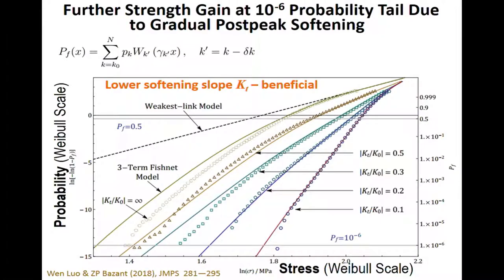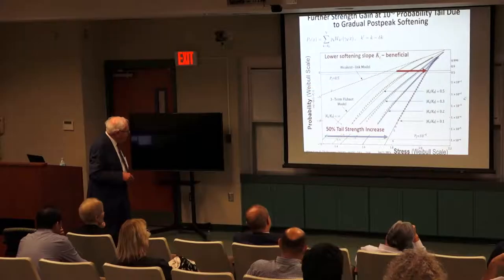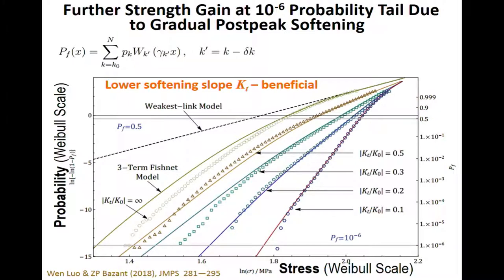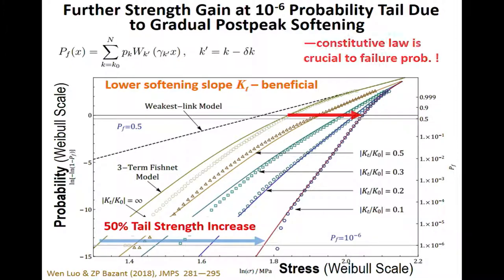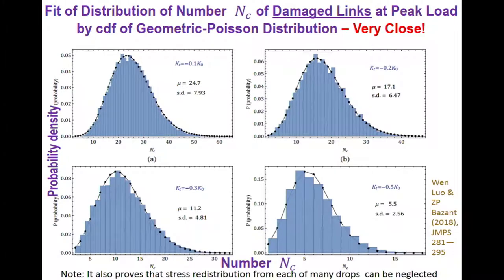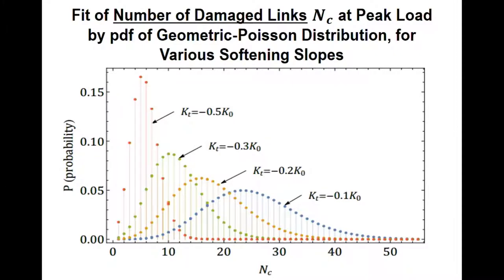And this is now verification by numerical simulations. Again, very extensive calculations, and they also give this kind of behavior. And you see the effect that there is a 50% tail strength increase at the probability line of 10 power minus 6, sorry. It's again a very significant effect even for these fishnets which are progressively softening. And these are the Weibull-fitted distributions, they are skew of course. And further comparisons for different slopes of the softening, small slope here to big slope, different behavior.